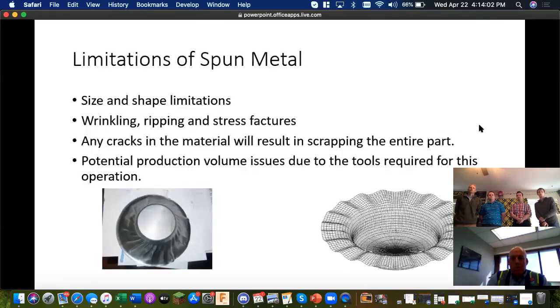So, some limitations of spun metal. We had some shape limitations from a few slides ago. Besides that, when you're doing the metal spinning process, if the material gets too thin, or if you use the rollers too fast, you can have some serious issues such as wrinkling, ripping, and stress fractures. Any of these failures will cause an instant scrap of the part. It is impossible to save a part that has any cracking in it without melting it down and starting from scratch. So you can have some potential production volume issues, balancing out going in too fast compared to getting parts that will work strength-wise.